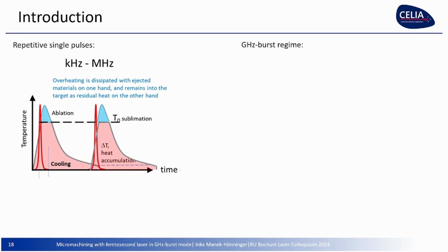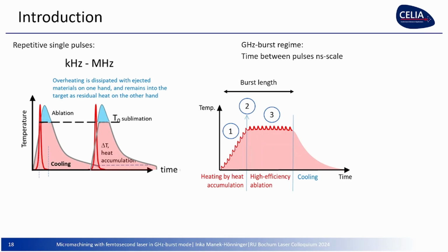There's a very nice paper, by the way, from Stefan Nolte's group, by Franziska Bauer, who did experimental studies and simulated that already at 200 kilohertz we have some residual heat. Then the next pulse comes, and the next, and so on. The residual heat saturates at a certain level, but lots of the energy is not used. So what happens in the GHz-burst regime? You have time on the nanosecond scale between the pulses within the burst, so the time is quite short and the heat is not really diffusing in that time, depending on the material, of course.